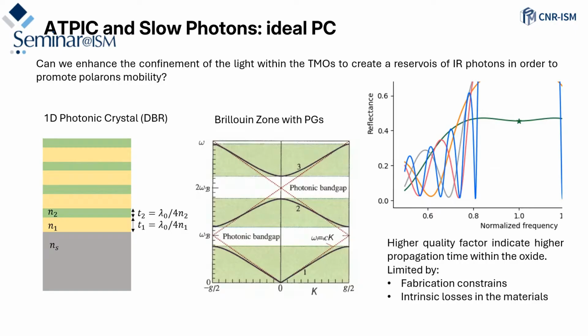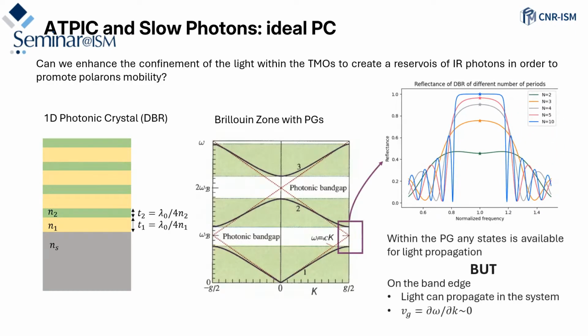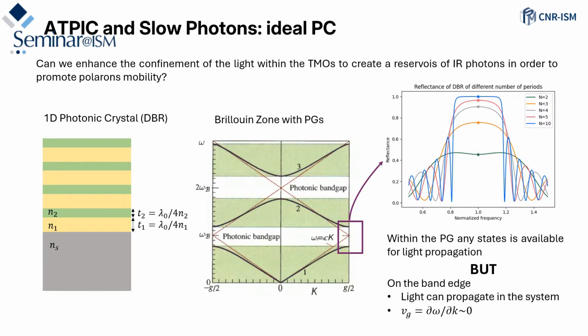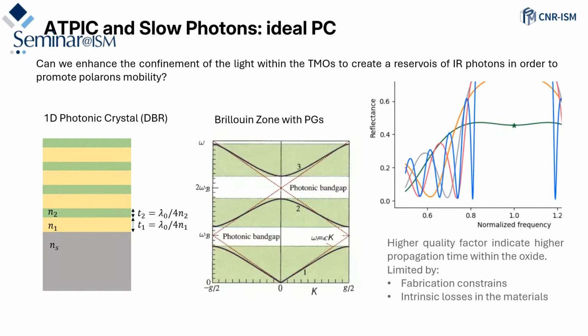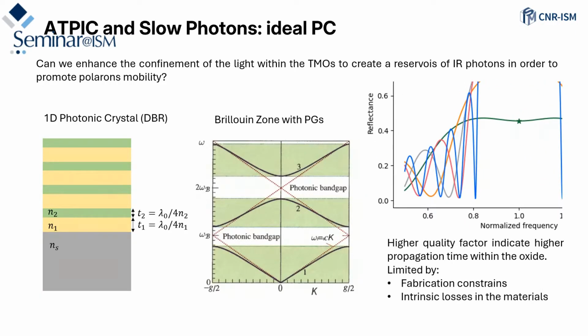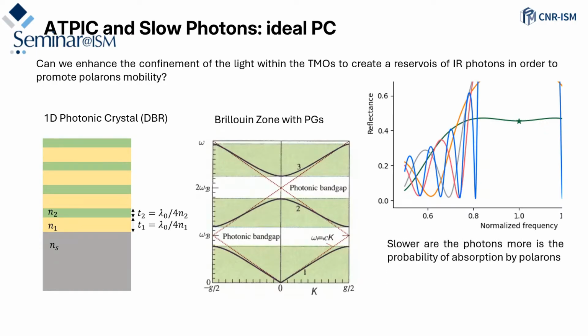Of course, the quality of these resonances depends on fabrication constraints. In this case, you have these narrow resonances just because you have more repetitions of the multilayer. But if you have, like here, just a few repetitions, those states are more broad, and that means that in that case you have more losses, and of course the velocity is higher. So of course you are limited by the fabrication constraints and intrinsic losses of the material, but the idea is that the lower the velocity of the photons within the material, the higher the probability that polaron can absorb those photons.